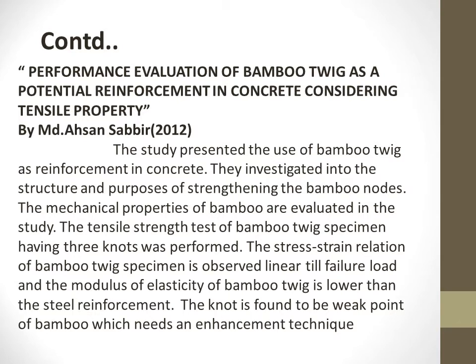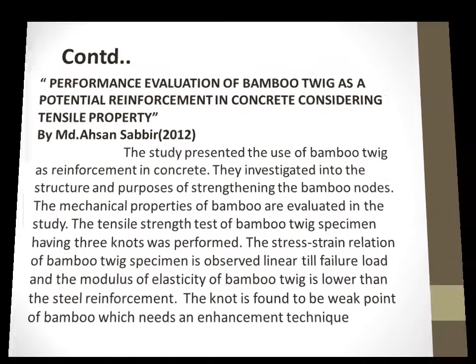This is another journal on the title Performance Evaluation of Bamboo Twig as Potential Reinforcement in Concrete Considering Tensile Property by Md. Ahsan Sabbir in 2012. The study presented the use of bamboo twig as reinforcement in concrete. The tensile strength test of bamboo twig specimen having three knots was performed. The stress-strain relationship of bamboo twig specimen is observed linear till failure load, and the modulus of elasticity of bamboo twig is lower than the steel reinforcement. He later concluded that the knot was found to be the weak point of bamboo, which needs an enhancement.